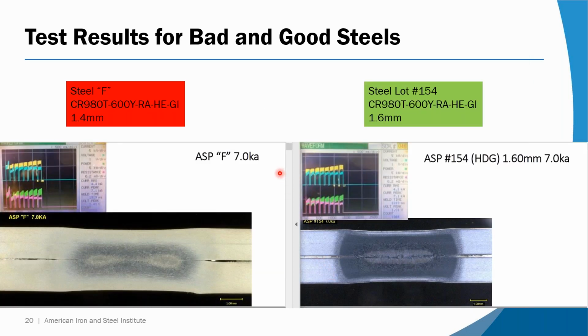So let's put these side by side and apply this progressive sloping weld schedule at a low current. In this case, we're applying 7 kiloamps. Now, I said we're using upslope, so when I say 7 kiloamps, I mean that we're ending at 7 kiloamps. Every one of the welds I show you here is going to start at 5 kiloamps, and by the time it gets to the end of the 8th pulse, it'll be at 7 kiloamps. So we're just trying to gradually put in more and more current in order to warm this up and try and get that Gleeble condition out here at the where the B crack might form.